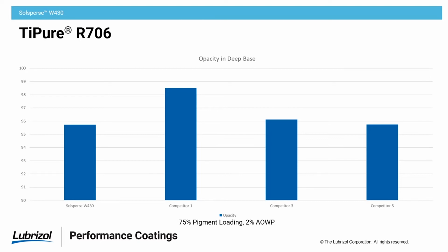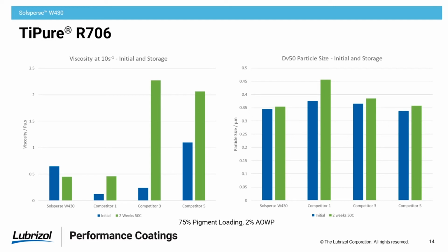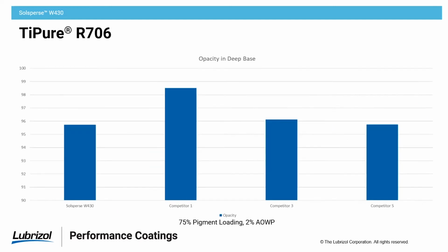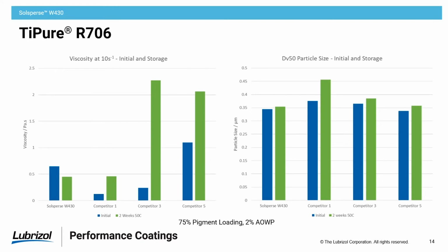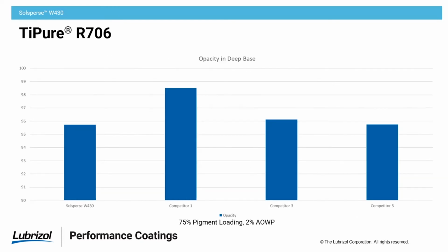And here we see that the W430 is pretty good, achieving the opacity. You'll see this competitor number 1, in fact, was a little bit better in terms of opacity, but not as good in terms of slurry viscosity. Generally speaking, there's a balance of properties that we're looking for. The cost and use with the W430 is much better than competitor one, which is a more high-performing additive, but is used quite a bit in industrial type applications.